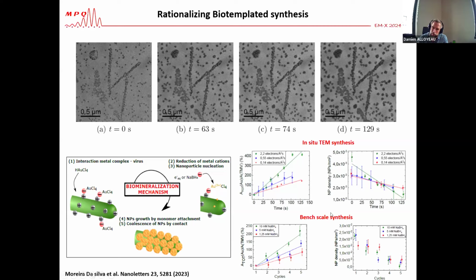And when you compare the result of in situ observation with bench scale synthesis, my colleagues have run the same experiment, except that they are using NaBH4 as a reducing agent with different concentrations, and they run different cycles of reduction, and we observe the result of the synthesis after each cycle. Same result: you see that you increase the concentration of reducing agent, you increase the growth speed, and also you increase the density of nanoparticles at the first cycles, and coalescence drastically decreases your density of particles.